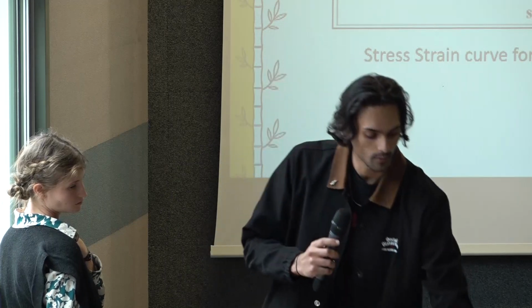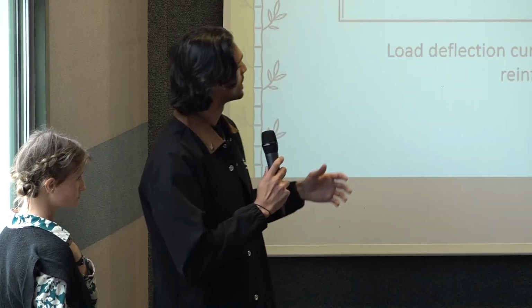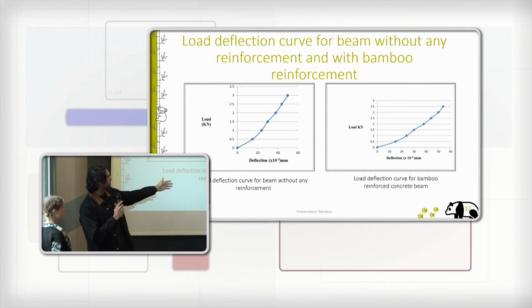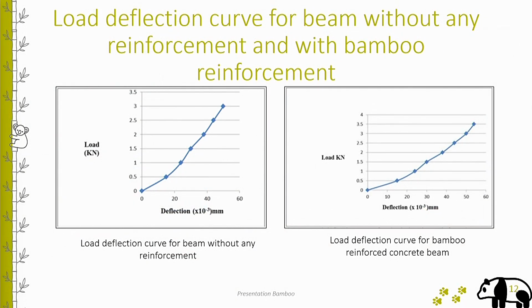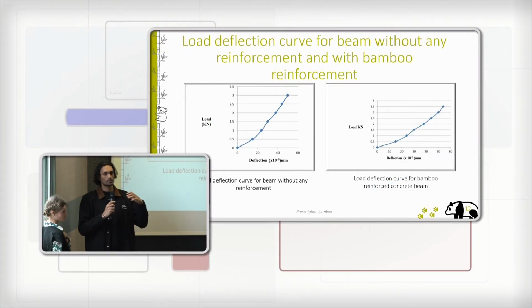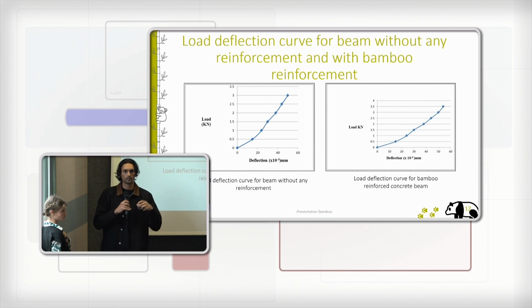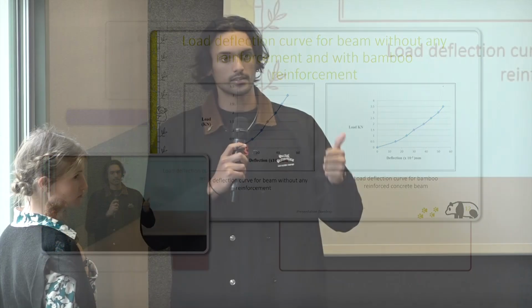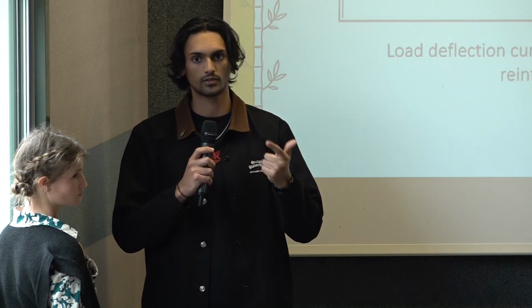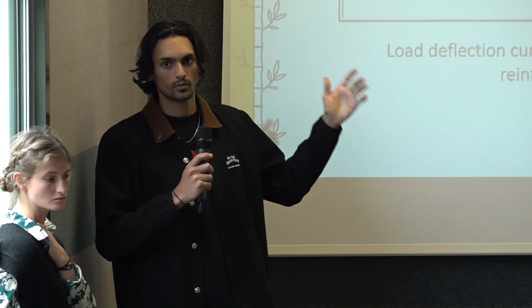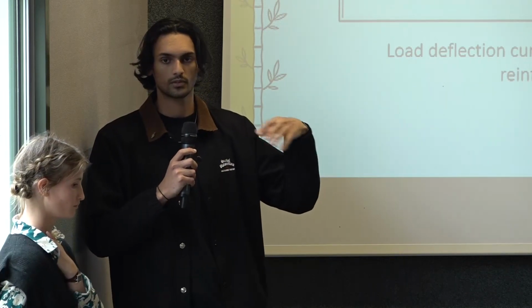Now, on the other hand, we have beams. Here is the load-deflection curve for beams without any reinforcement and for the reinforced concrete beam. We can see that for the same deflection on the curves, we need to add more load for the reinforced beams. So we have a better flexural strength for the reinforced beam. To conclude, when we add bamboo fibers, the elastic modulus increases and the flexural strength increases too. So we can say that we can use composite concrete with bamboo fibers for buildings.